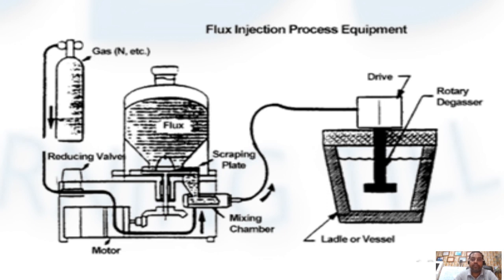rotor dispersion. When flux injection is coupled with rotor dispersion, as you can see in this image, better results are obtained. In this situation, the mixing kinetics between the flux agent and the metal bath are increased, as the rotor action creates much better dispersion than a simple static flux injection. Flux injection with rotor dispersion is usually practiced to achieve degassing through both the flux compound and the carrier gas itself. In addition, proper flux composition will help clean the bath by combining with oxide in the metal to a great extent and delivering many of these to the surface ready for skimming.